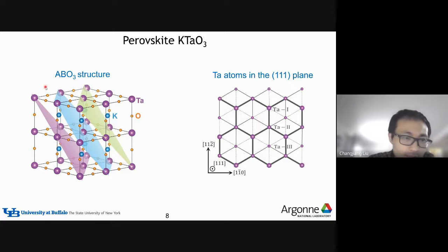So this is just a structure, perovskite structure, which has ABO3 structure. And now on the right is the top view from the 111 crystal axis. Once you view the crystal along the 111 axis, the lattice can form a buckled honeycomb shape. So basically, these atoms with different size represent atoms at different layers. So between adjacent layers, the atoms can form a honeycomb structure. And people found that this 111 interface can show very interesting electronic structure, and they can exhibit some unusual physical properties.